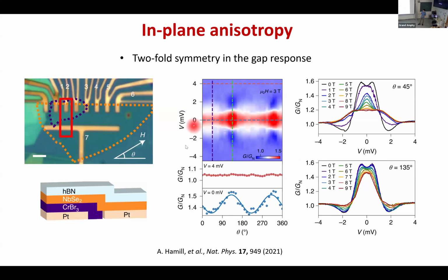Also, they move on to measure the gap as a function of an in-plane field. When you rotate the in-plane field, one can see that this is deep in the superconducting state. You can apply the in-plane field at an angle of 45 degrees, or rotate another 90 degrees to 135, and the response is quite different. At 45, when you apply the magnetic field up to 9 Tesla, you can suppress these features very easily. But if you rotate another 90 degrees, these features stay up to 9 Tesla.